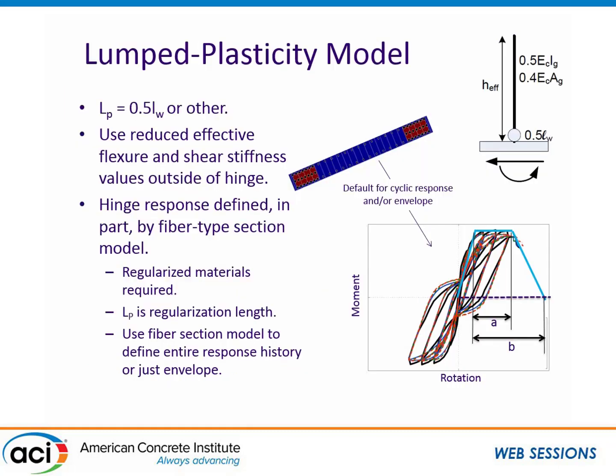If you don't do that, as you add more and more elements you get a more and more brittle response; with only one element at the bottom story you can get an incredibly ductile response with no basis in reality. Applying this approach for a force-based element to a number of different tests, we can predict strength quite well, displacement at yield quite well, and displacement at onset of strength loss quite well. That same approach also works with a lumped plasticity model, where the length used is just your plastic hinge length.